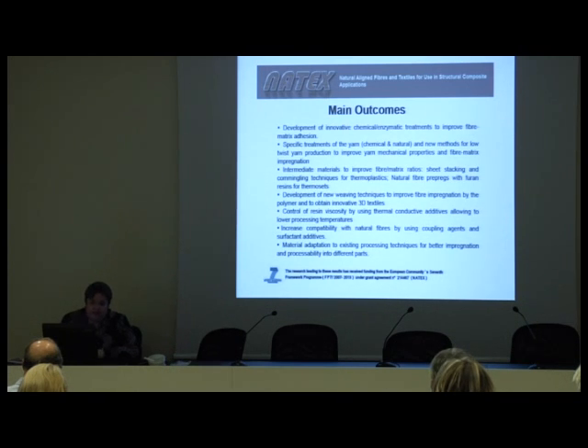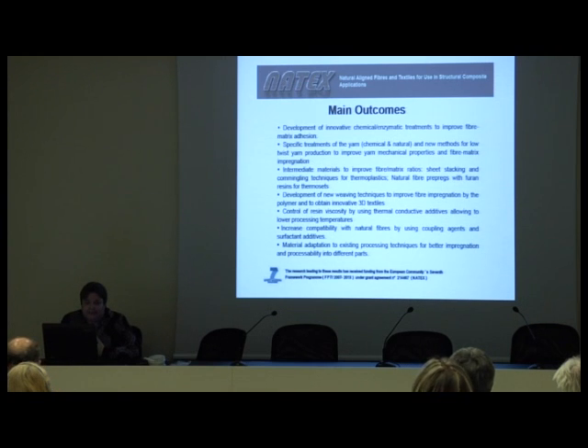We also have a line of research in working on reducing, controlling, but mainly reducing the viscosity of the resin using thermal conductive additives, allowing lower processing temperatures in order to reduce the degradation of the fibers. Increased compatibility with natural fibers by using coupling agents and surfactant additives, and material adaptation in order to fit all these in the traditional composite processing technologies.